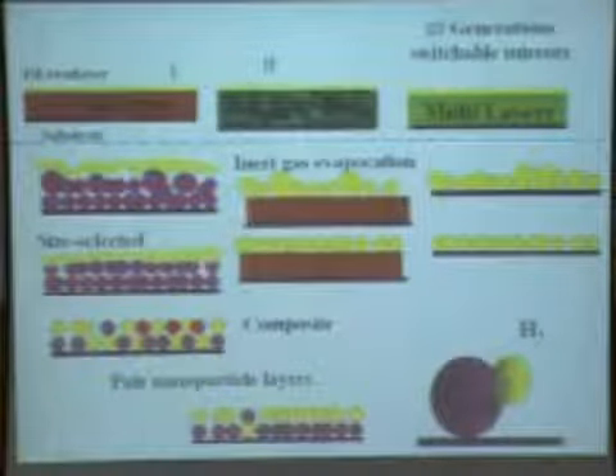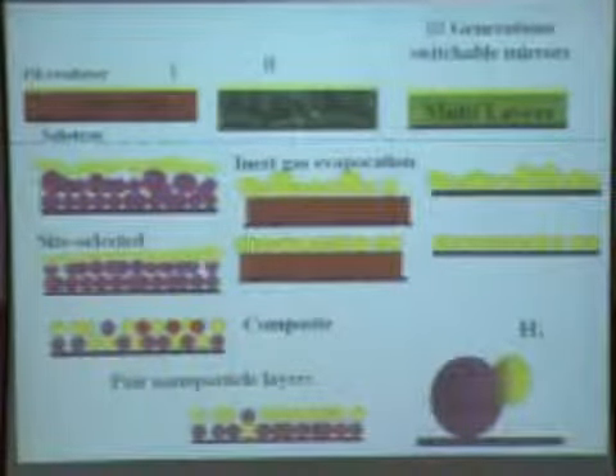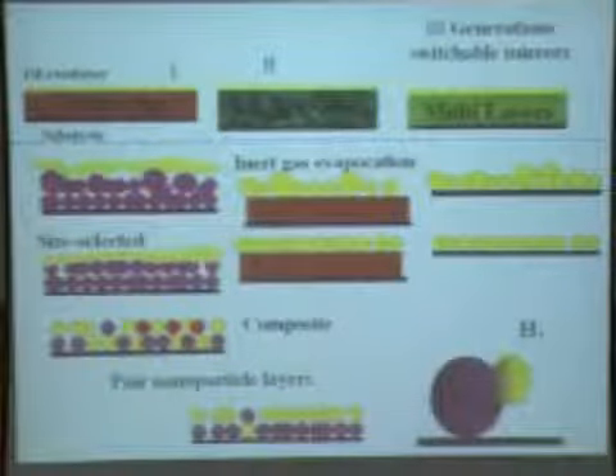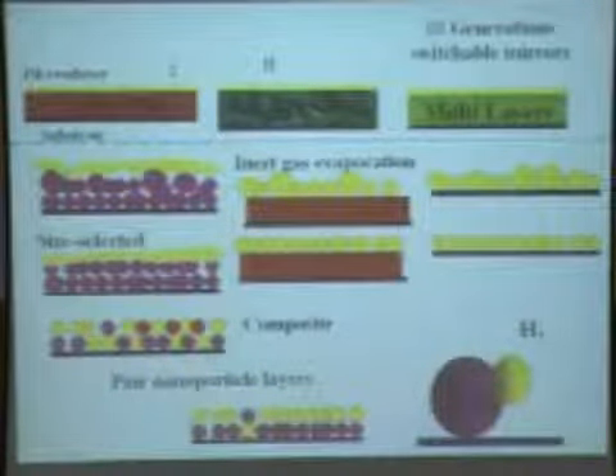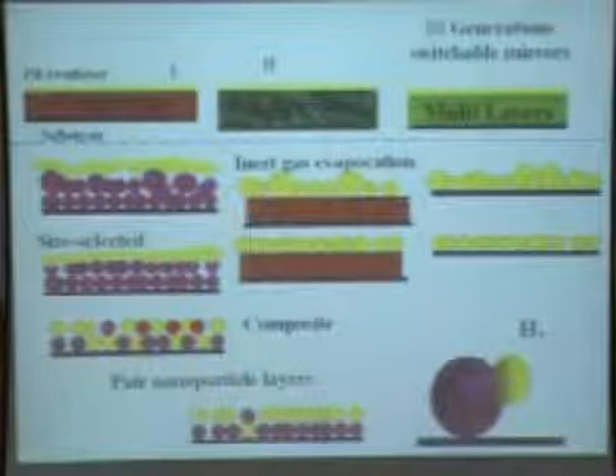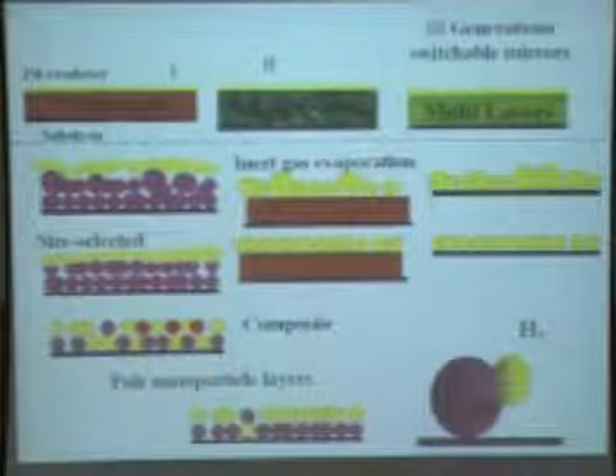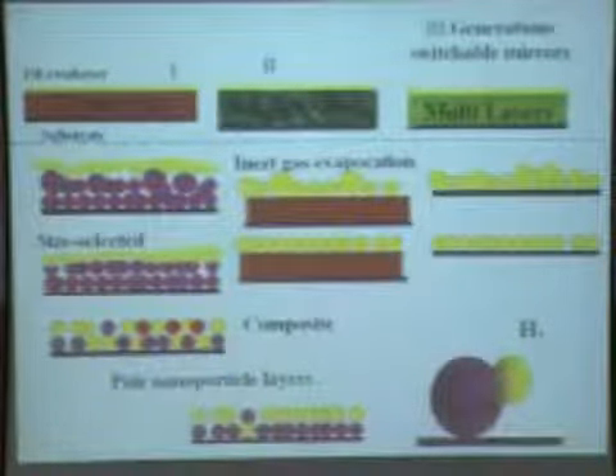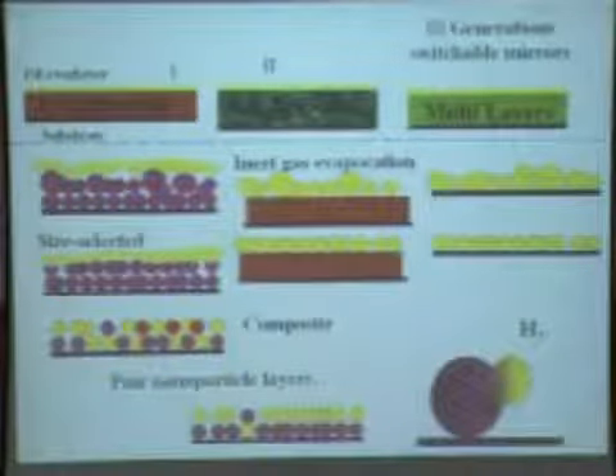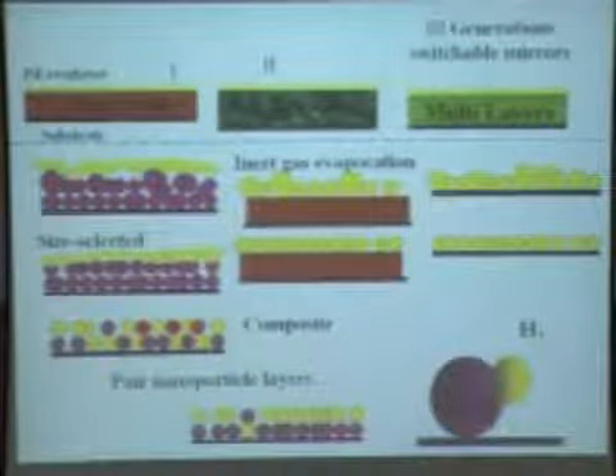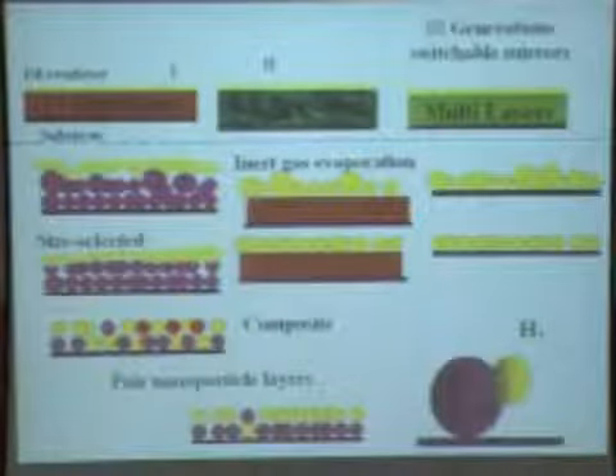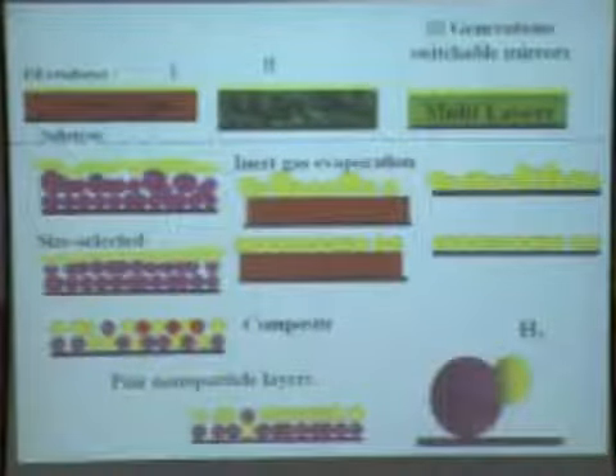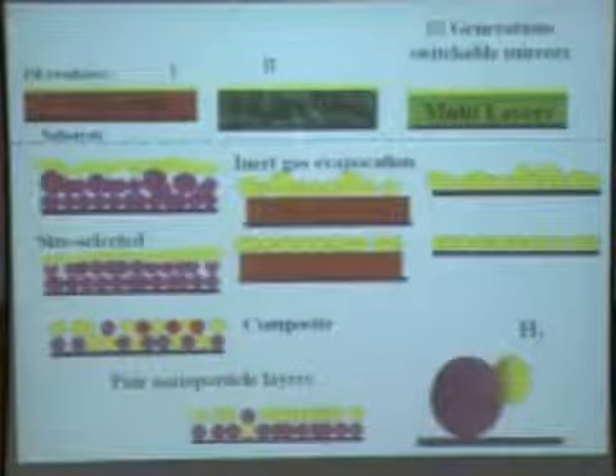Okay. The advantage, which I did not mention, when you go from thin films to polycrystalline to size selected nanoparticles, is that there are other important parameters also. One of them is hysteresis. This is the change in the electrical or optical properties as a function of increase and decrease in the hydrogen concentration. When you go through the complete cycle, there should not be any hysteresis.